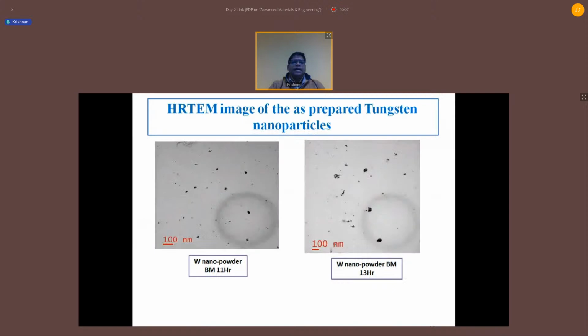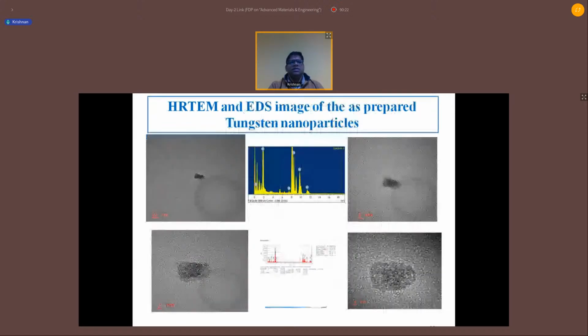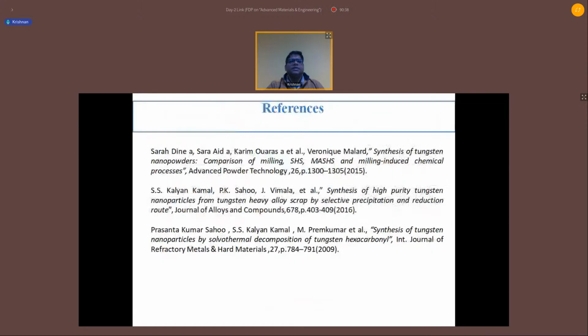This is the TEM image of the tungsten nanoparticle at 11 hours and 13 hours. We have got this at the 100 nanometer scale with more than 1 lakh magnification. And this is the HRTEM and EDS image of the tungsten nanoparticle. We got fringe patterns for 10 nanometer, 5 nanometer, 2 nanometer, and 1 nanometer particles. And this is the EDS image. So these are the references of my work.